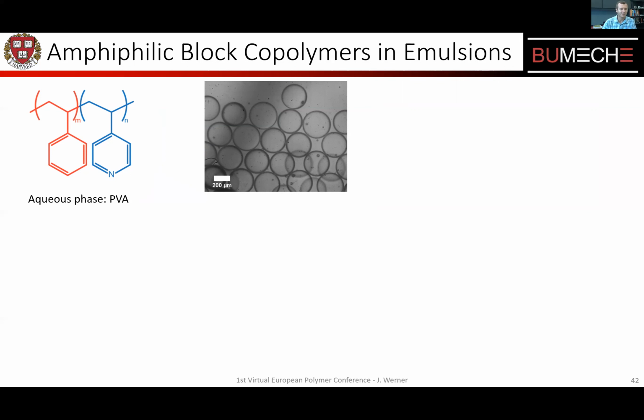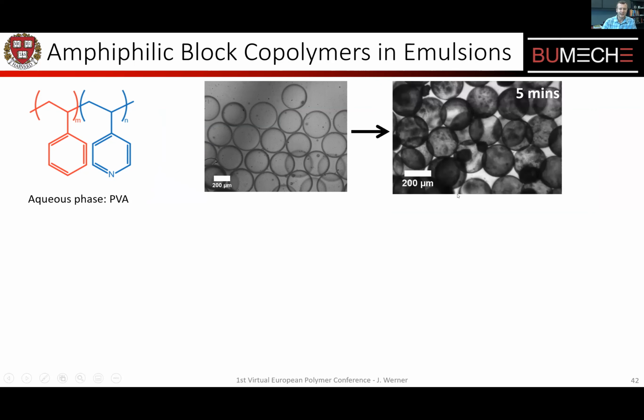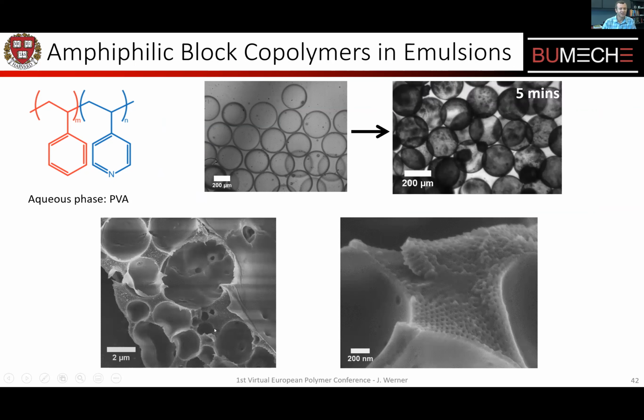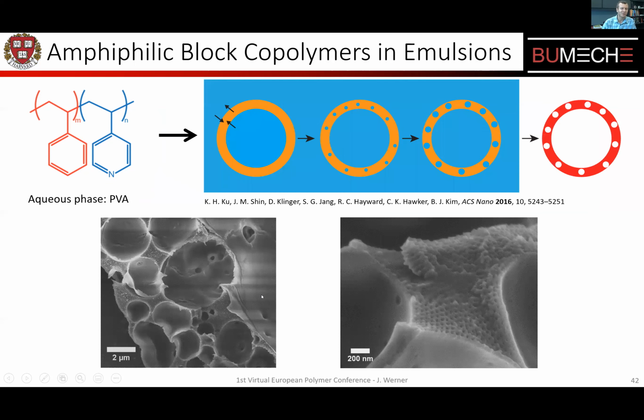And the reason for that was that when we used no salt in our solutions, what we found is that our capsules during the evaporation process turned very heterogeneous optically. And in the SEM image, we found these large voids inside the shell. Between the voids, we had our block copolymer self-assembly. And we hypothesized that that is due to self-emulsification of water into the oil shell due to the amphiphilic block copolymer, that then leads to water drops that phase separate within the shell, which has been seen in single emulsion oil drops just a few years ago as well.